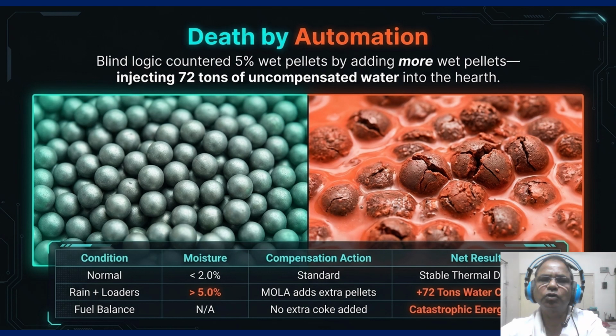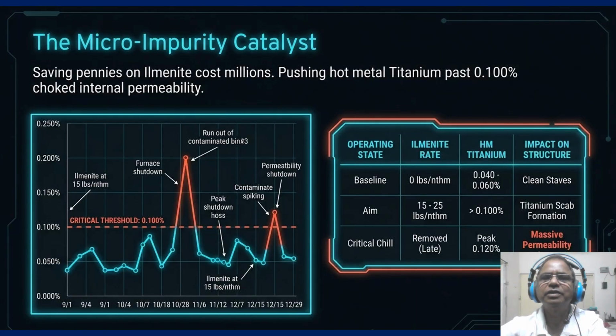So, as the water was draining the energy, a micro impurity was busy choking the furnace's internal breathing. So, the micro impurity catalyst: saving pennies on the ilmenite cost is millions in production. Follow the orange trend line for the hot metal titanium. Our baseline aim is 0.04 to 0.06%.